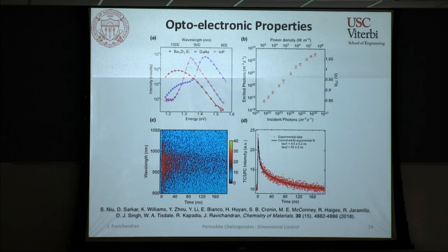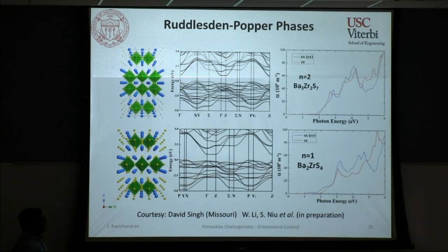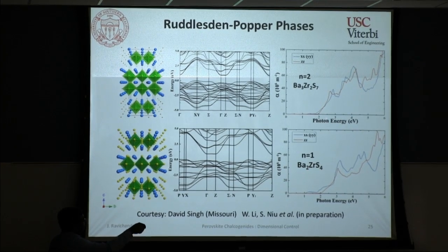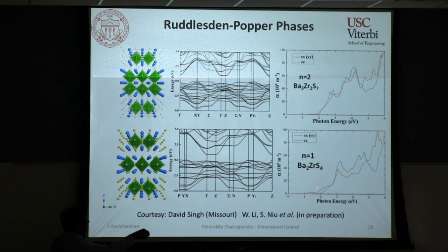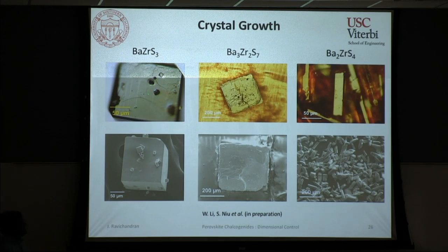So continuing on this front, we got curious and wondered why this redshift happened. To address this issue, we looked at the second compound in the same class, which is barium-2 zirconium sulfur-4, and that also showed very similar anisotropy in the absorption coefficient in the two directions, and also showed a very similar redshift to what we saw earlier. So it seems very spooky now that more than one of these compounds are theoretically predicted to have redshifting despite having this layered structure.